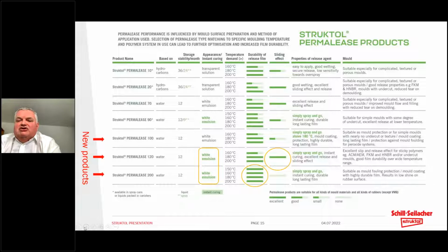Instant curing means that we no longer have to take into account so much the time after spraying before molding. Many products in this sector will say apply to a hot mold and then wait 5, 10 or 15 minutes. This is necessary for the cross-linking of the coating in order to achieve the higher state of cure and the durability. Instant curing technology changes the cure system and the catalysts that we have in place and reduces that very much from multiple minutes to 1 or maximum 2 minutes.